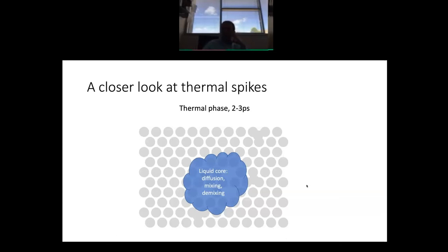So all those atoms that are in the core of the thermal spike very quickly become an equilibrium liquid, right? So they reach the form of an equilibrium liquid at very high temperature, maybe 10,000 degrees or something like that, but it is an equilibrium liquid. And in that liquid core, you get all the regular things that occur in a regular liquid. For example, diffusion, mixing, demixing, all those things can occur in that core, okay? And as a result of that, all the vacancy interstitial pairs, or all the Frenkel pairs that happen to be inside or near that core, recombine, right?